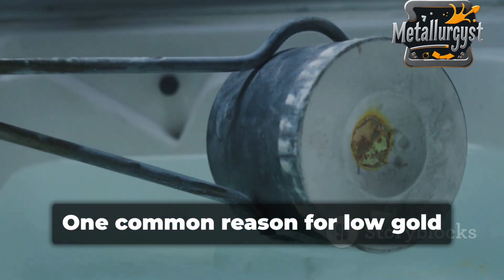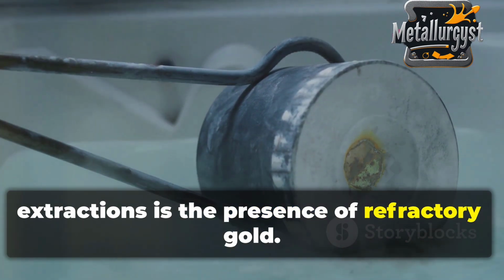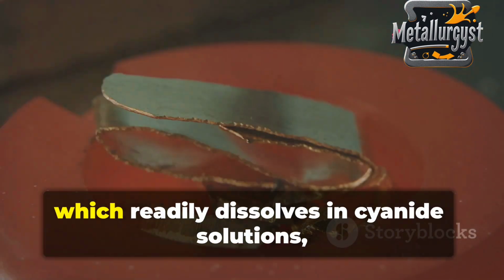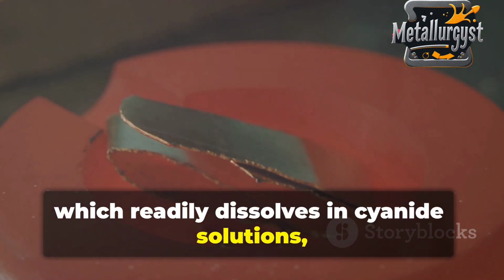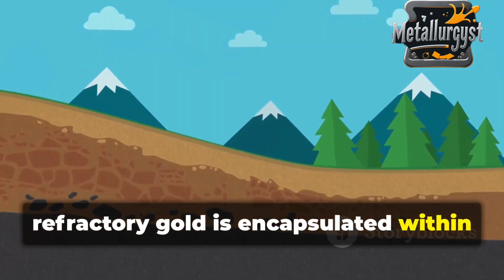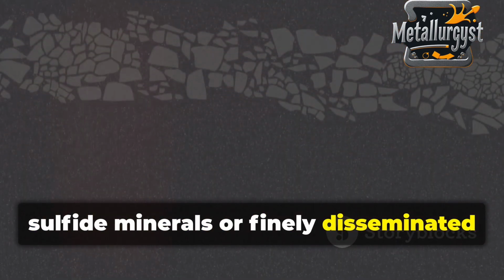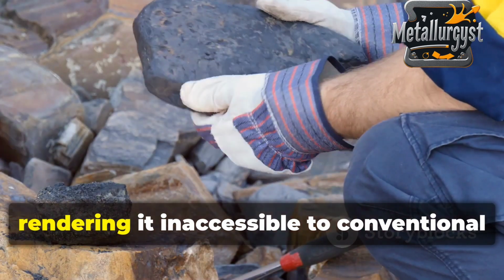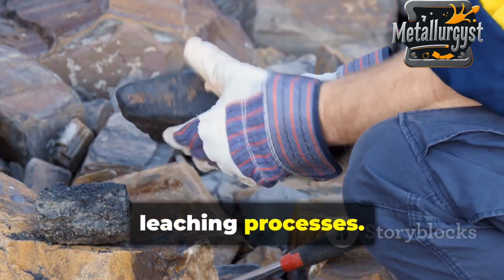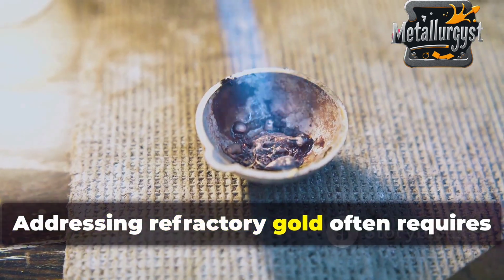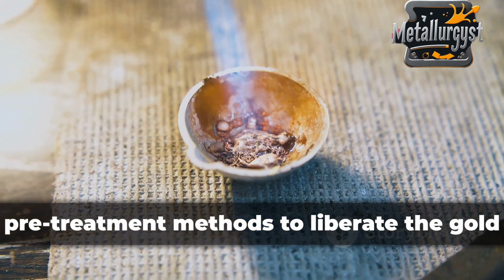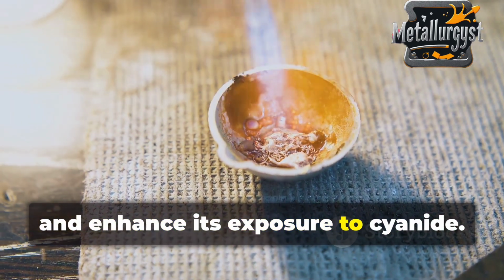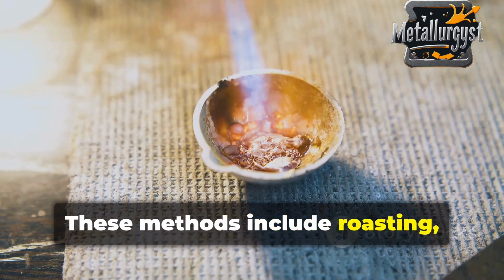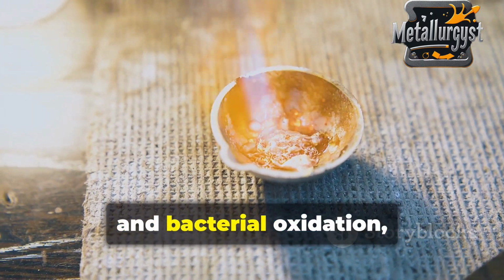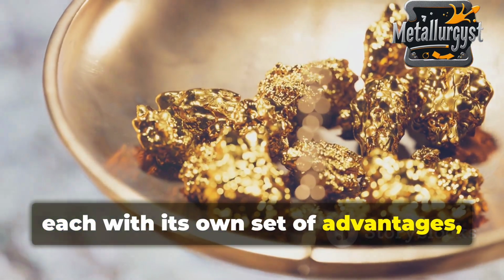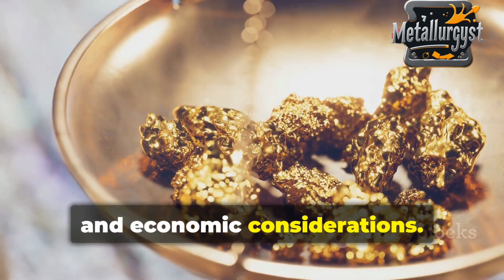One common reason for low gold extractions is the presence of refractory gold. Unlike free milling gold, which readily dissolves in cyanide solutions, refractory gold is encapsulated within sulfide minerals or finely disseminated within the ore matrix, rendering it inaccessible to conventional leaching processes. Addressing refractory gold often requires pre-treatment methods to liberate the gold and enhance its exposure to cyanide. These methods include roasting, pressure oxidation, and bacterial oxidation, each with its own set of advantages, disadvantages, and economic considerations.